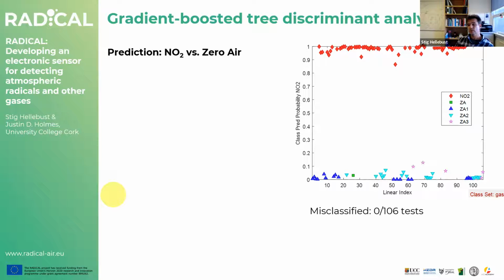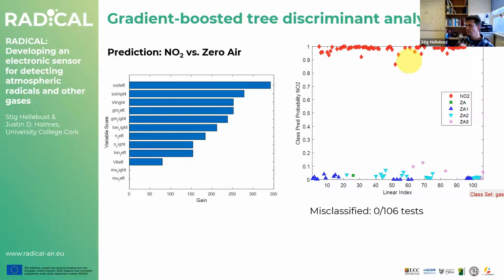And let's not be too ambitious to start with. Let's just say, can we distinguish between tests where the device was exposed to zero air and the tests where it was exposed to NO2, and never mind the concentration at this point? And the answer is yes, because what this model comes up with is a probability of prediction, and it turns out that of all the 106 tests that we have done here so far, they were all classified correctly as relating to NO2. So of course this is a simple system. It's either zero air or zero air with some NO2 in it. But what's interesting as well is that we can look at what are the important variables. And again, it turns out that for this particular model, the shape, the slopes seem to be the most important parameters here. So this is something we can bring with us maybe when we are looking at surface functionalization.